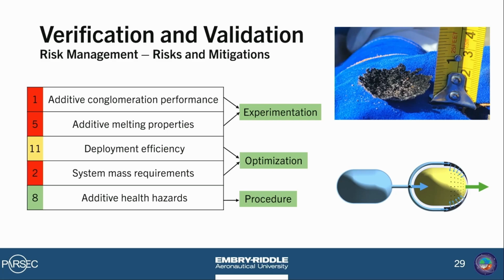And then the second critical risk I'd like to address is the additive melting properties. Just a quick note here, I did combine 2 of those critical risks into one because they both dealt with thermal properties, so that's why there's 3 critical risks instead of 4. The melting properties deal with 2 cases in the rocket plume. One, where the heat of the engine does not melt the additive enough to be an adhesive, and 2, where the additive gets melted too much and is unusable.